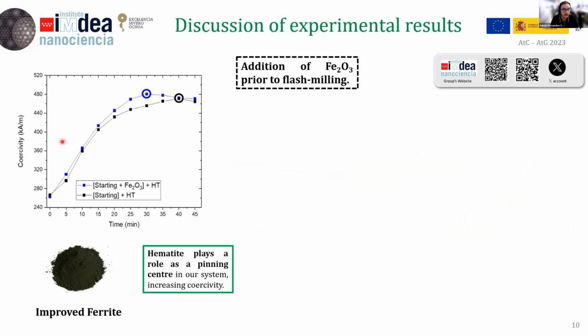process. So here you can see the comparison of the coercivity evolution as we increase the milling time for both experiments. In black, the one without the hematite content addition prior to the flash milling, and the other one with the addition of the hematite prior to the flash milling. So first of all, we can see that we reach the maximum coercivity point at lower milling times for the second experiment. And that we are achieving higher coercivity values for this case.